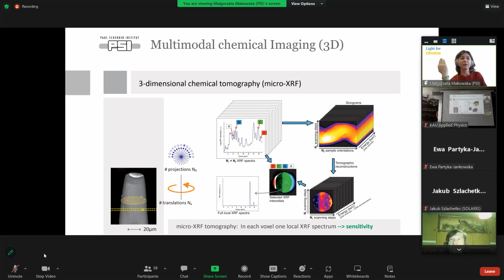So we scan the sample in X and we rotate the sample. And then for each pixel, essentially, we get the spectra, in this case fluorescence spectra for each pixel. And for each rotation, again, another one and another one. From this signal, for each energy bin, we can construct sinograms. And then using tomographic reconstruction algorithms, we can obtain fluorescence contrast images for each energy. And of course, this we can do for several slices or many of them, and then finally obtain the 3D image.